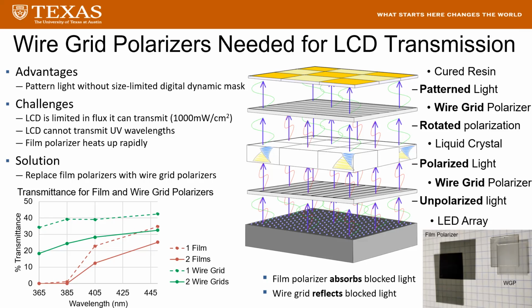You can see some transmittance data for film and wire grid polarizers in the bottom left-hand corner. And you can see that wire grid polarizers transmit light at every wavelength in the UV and near UV region much more efficiently than film polarizers, even down to 365 nanometers. In addition, since wire grid polarizers are reflective rather than absorptive polarizers, they don't heat up as rapidly under illumination, allowing you to illuminate the LCD at much higher intensities without overheating the screen.